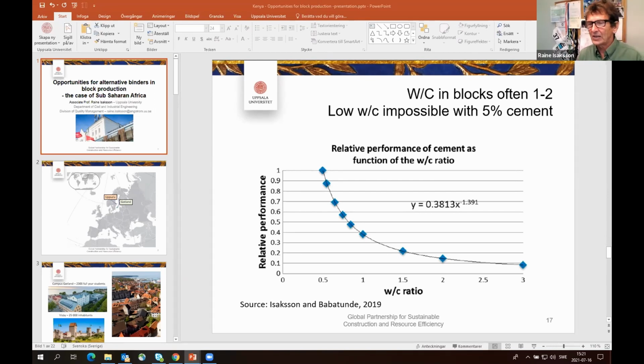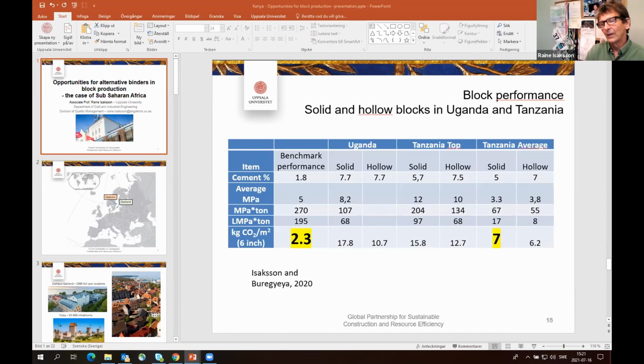Now, could this be changed somehow? Well, maybe improve a little bit with hollow blocks, which I have tested, but not substantially. So this is a big problem: the 1 billion blocks produced in Dar es Salaam and in many other countries use maybe 20% of the cement potential only. So all that emission is going out for nothing because we use only one part of the capability.